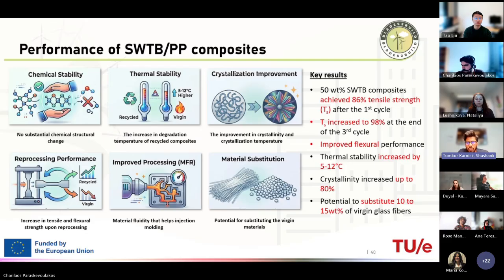And on the other hand, the crystallinity of the material also matters the most, because we are dealing with polypropylene material, which is a semi-crystalline material. So when we assessed the crystallinity of these materials, we understood that there was a huge increment in the crystallinity index of these materials, where it actually went up to around 80%.